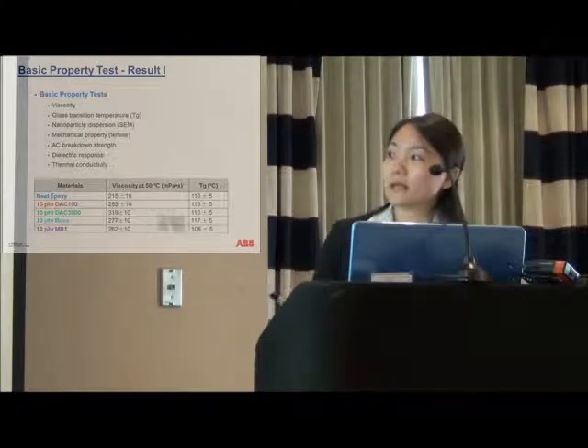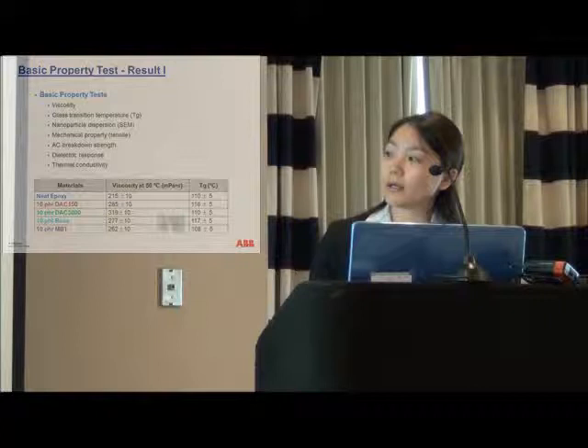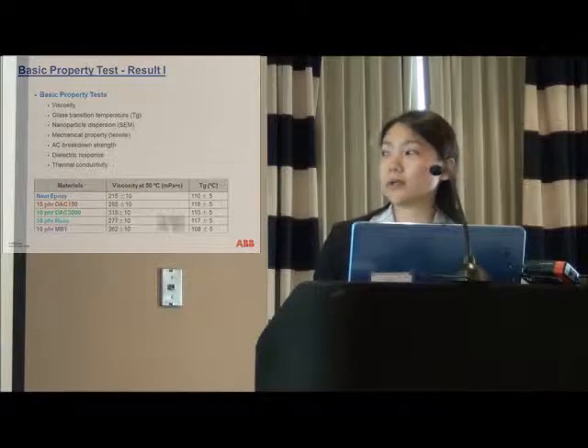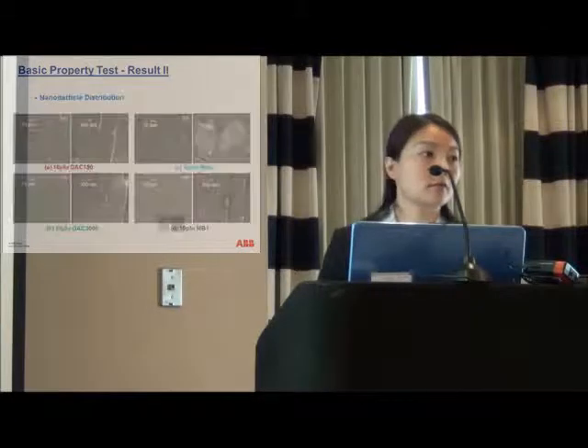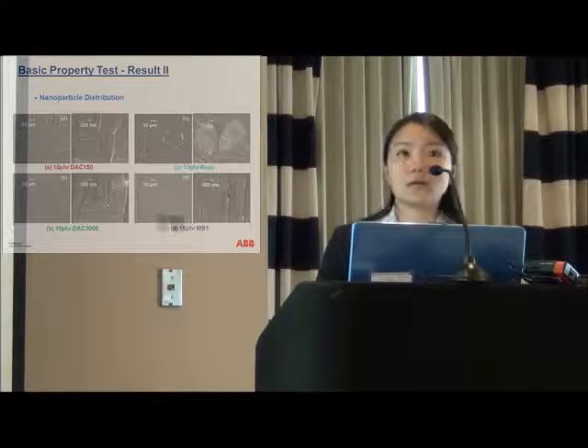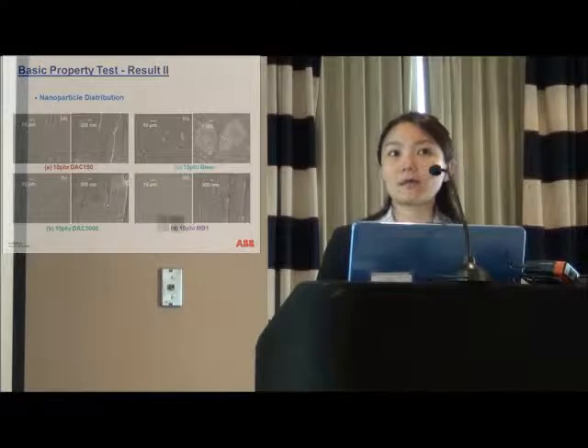The glass transition temperature shows, more or less, no significant change for the nanocomposite, since we are not using a very high quantity of particles.